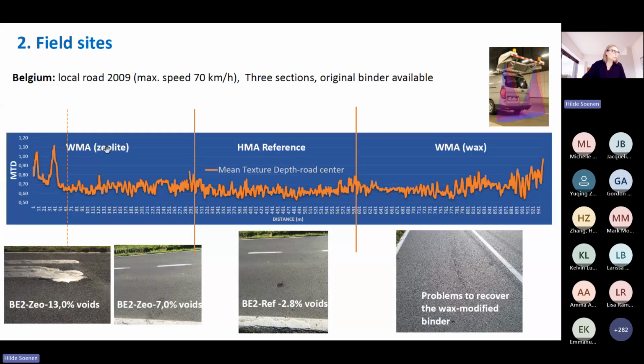But the zeolite section we could split into 2 because the first part was really suffering from raveling. You already see it has been repatched. So we took cores in between these maintenance areas. And then we had a second part where we could also take cores, which had mainly raveling, as you can see here. The performance on this test track was, on one hand, done by a visual inspection from the Belgian road authorities, but we also applied an automated scan, and here you see the mean texture depth, which was in the road center. So there was quite some raveling, which was not due to traffic.